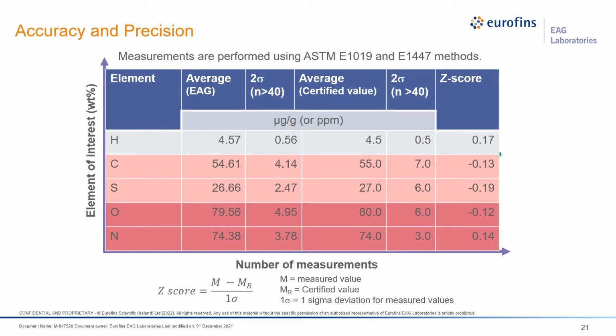So let's look at the real data here. This table gives an example of how EAG measurements compare with certified values of hydrogen, carbon, sulfur, oxygen, and nitrogen. The average represents our internal statistical process control data acquired routinely for reference materials. As can be seen, the z-score is close to zero, meaning the difference between EAG average values and the certified values is very little. Please note that the z-score is normally calculated using 1 sigma spread. Also, these measurements are done using ASTM methods.